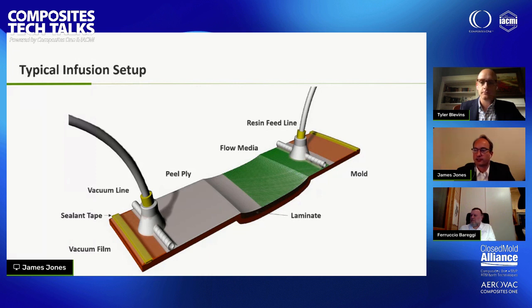So once the dry reinforcements are loaded into the mold, they're covered with a peel ply or a perforated release film. As the name suggests, the peel ply can be peeled off the cured laminate. So this allows us to remove the processed materials, and it also gives us a nice textured surface for secondary bonding. The flow media is applied next. Since we're using very compact, high fiber content laminates, we need something to increase the laminate permeability, the ease with which the resin can flow through it. So we add a flow media that's fairly open construction that allows fast flow of the resin across the surface. As Ferruccio will talk about a little bit later, there's also some combination products where you can put some of these materials down in one step.